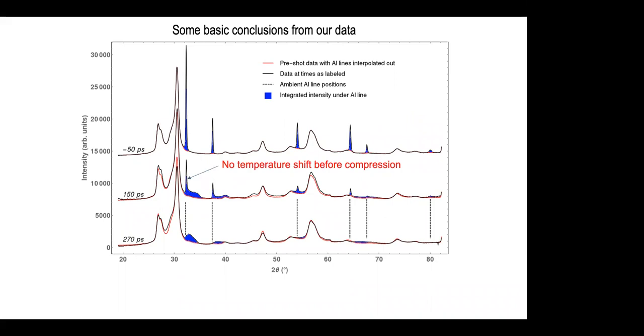It's important to note here that at some of our higher intensities, which range above 10 to the 11th watts per centimeter squared, we were a little bit concerned about preheating. If the intensities are very high, then potentially X-ray generation can occur. And because that can also penetrate the entire sample, you could have preheating, which would change its shock response because the initial material changes a little bit.